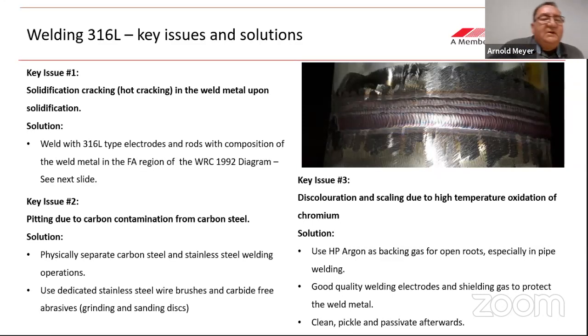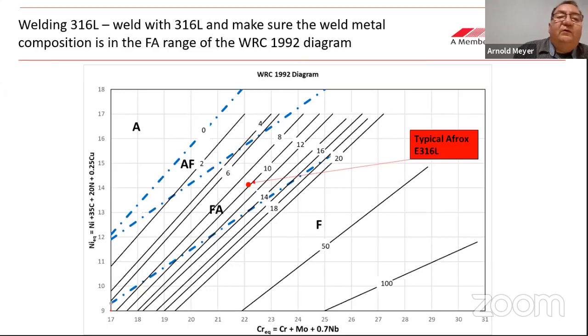Then if we move on to the 316L, the three key issues are exactly the same. You weld 316L always with 316L. You don't go to another type of stainless steel. But a very, very important thing here is, if you look at the 1992 diagram for 316, you must make sure that the electrode or the welding consumable that you buy has a composition that is very close to the middle of the FA region of that diagram. And the typical Afrox one is there. Any other reputable manufacturer of electrodes or consumables will know this and will also give it like this. You get people that will not give it to you like this. Don't buy those electrodes. You will have hot cracking problems with your 316.